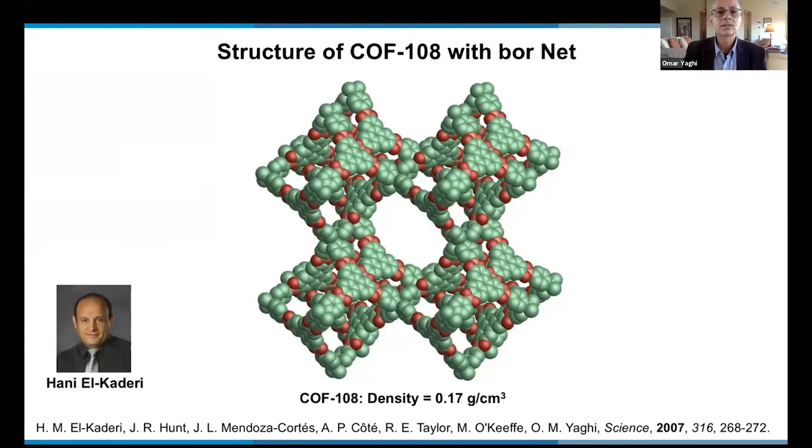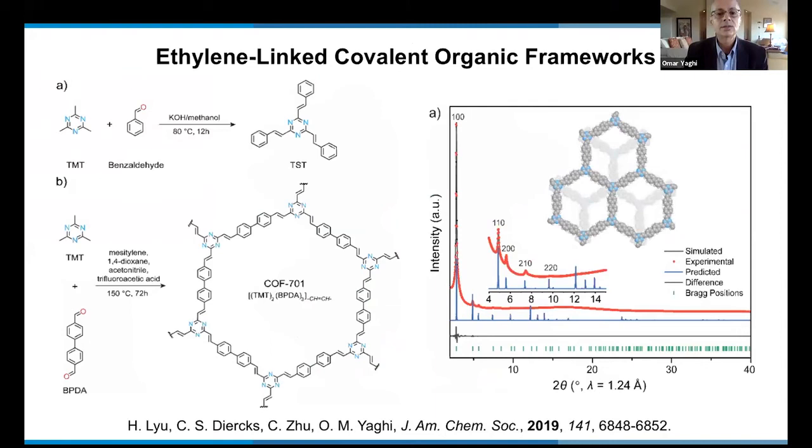Well, the ultimate, of course, is to crystallize carbon-carbon bonds. And so now you see how we use slightly different conditions, now adding trifluoroacetic acid. The trifluoroacetic acid is sort of a modulator that allows us to reverse this reaction during its formation and make crystals. See, it's fairly crystalline material. And this is a slipped graphitic structure, which we can refine from the powder diffraction. But see, it's entirely linked by extremely strong bonds, C=N double bonds and C=C double bonds. This is an extended 2D structure. Again, it's crystalline. It can be modified without losing its crystallinity. And it is very stable.